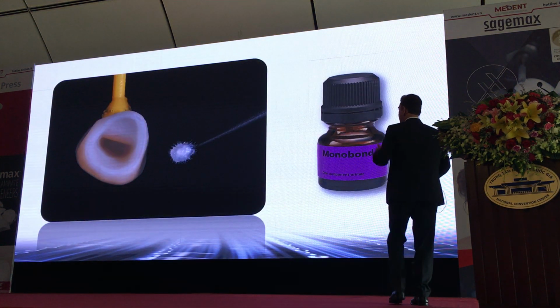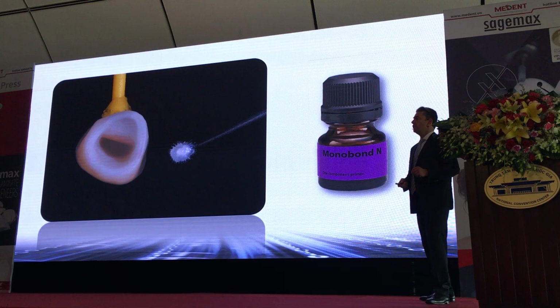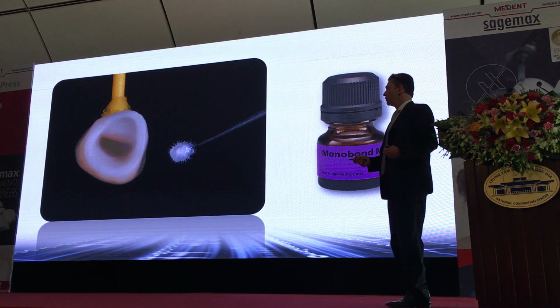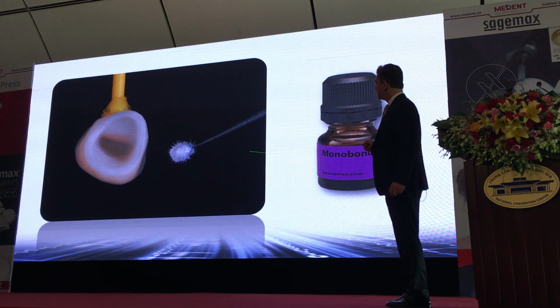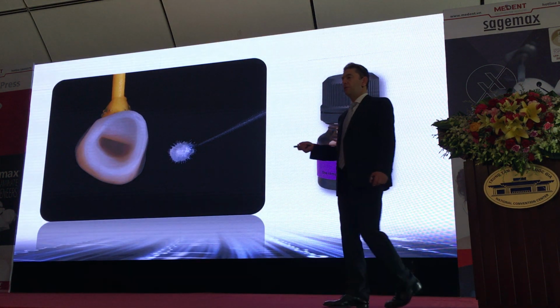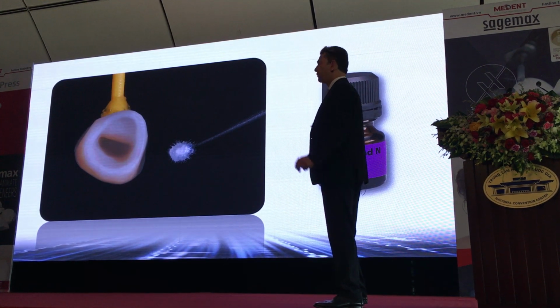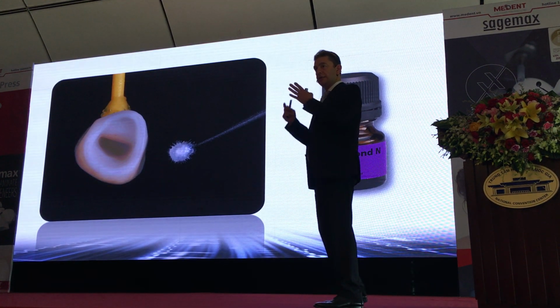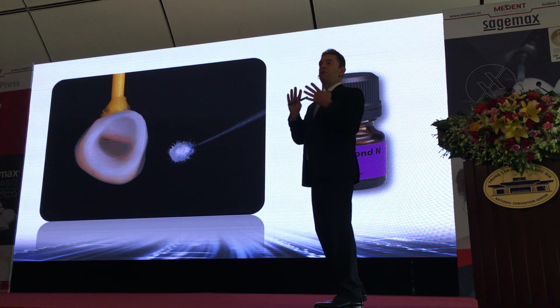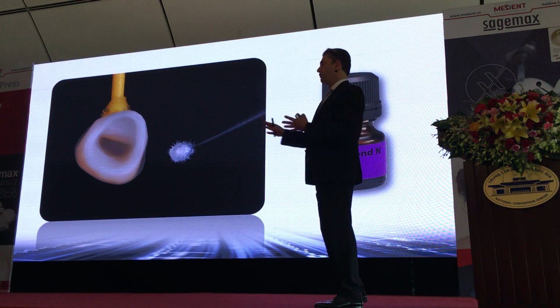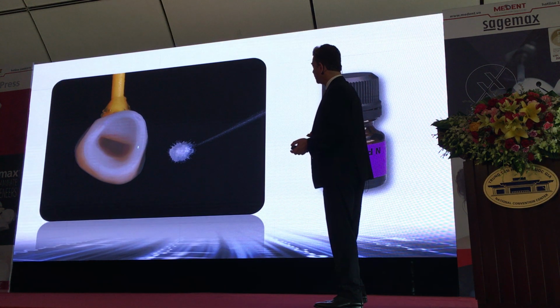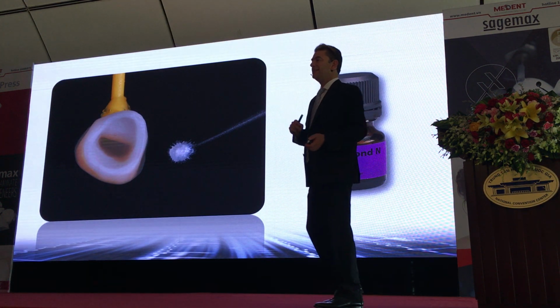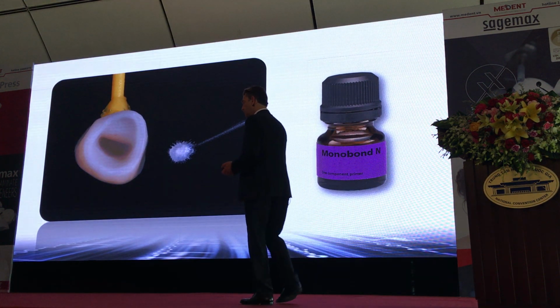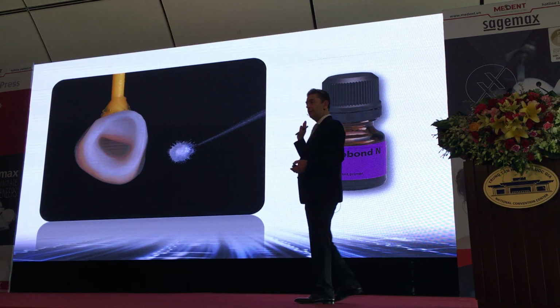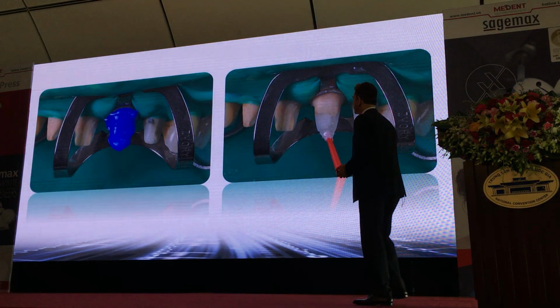Then we rinse it off, and we need to create a chemical bond with Monobond. So we have Monobond N here, and that contains MDP also, but it also is a silane methacrylate. So this can be used for almost all restorations. Yeah, it doesn't matter if you use it for zirconia or for glass ceramic. So you can use this for everything. So we apply this and leave it for about 60 seconds. After that, we just dry with air, and then we are ready for cementation.